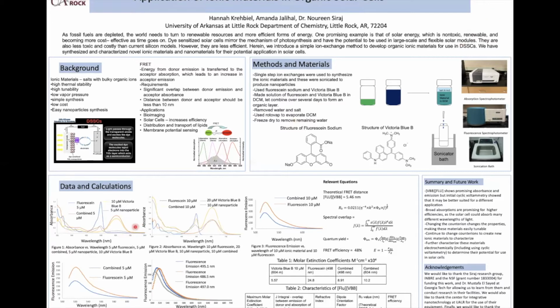Here for our absorbance graphs, we can see that we have an increase in absorbance from our parent materials to our combined, both at 5 micromolar and here with 10 micromolar. That's one good sign. And then for our emission, we can see that it's actually decreasing from the parent to combined. This is a good indicator that FRET is occurring because energy has to be transferred from the parent compound, the donor material, to the acceptor in order for FRET to occur.